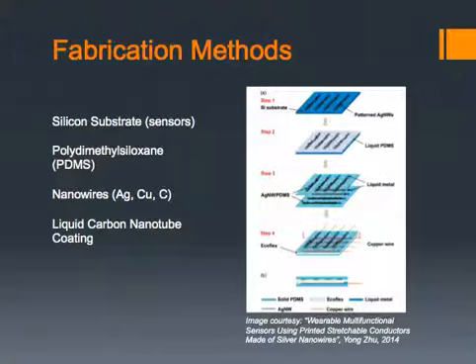New fabrication methods have been developed to ensure relatively easy and consistent reproduction of these nanomaterials. Common techniques involve the use of a silicon substrate on which nanomaterials such as silver nanowires are deposited. These materials are subsequently covered with PDMS and allowed to cure. The PDMS layer helps give the material an added flexibility, while the nanowires provide electrically conductive properties. These steps are demonstrated in the diagram on this page.